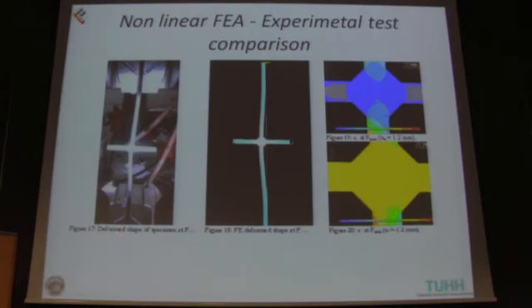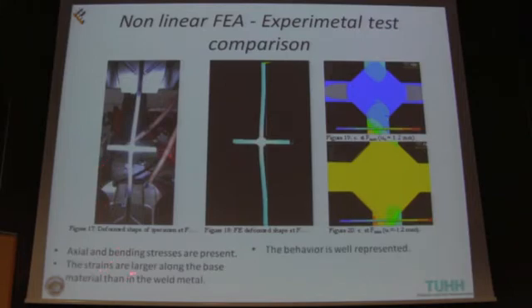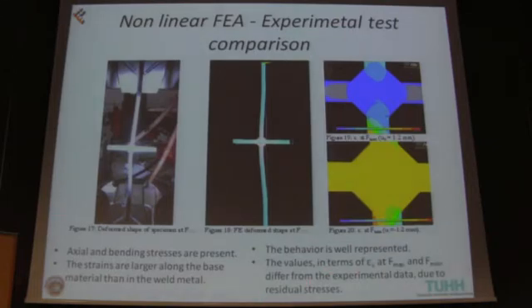Obviously, a comparison between the two techniques was made. Here we see the deformed shape of the specimen in the experimental test, and here we see the deformed shape of the finite element model. The finite element model also captures the bending strain for F max and F min. And the strains measured by DIC are larger along the base material than in the weld metal. This means that the behavior is well represented, but the values in terms of strain along the X direction still differ from the experimental data. This is probably due to the residual stresses.